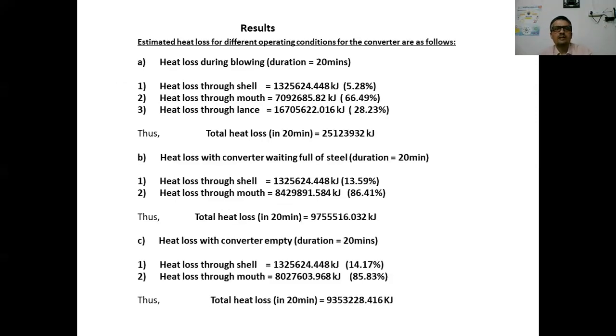Under different conditions, we have found that the heat loss by radiation has the highest contribution, and the heat loss through the shell has the least contribution. And of course, the heat loss through the lance also has a significant contribution. But all these contributions are dynamic in nature.